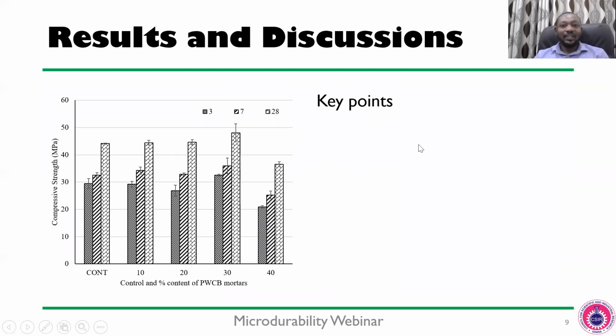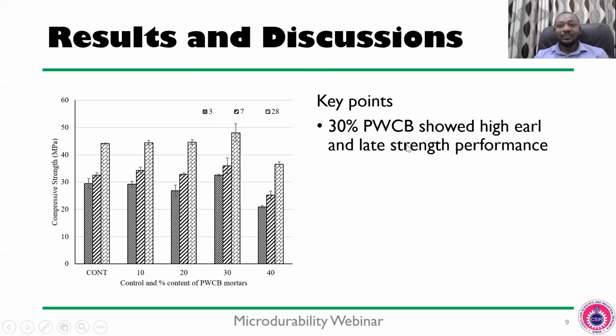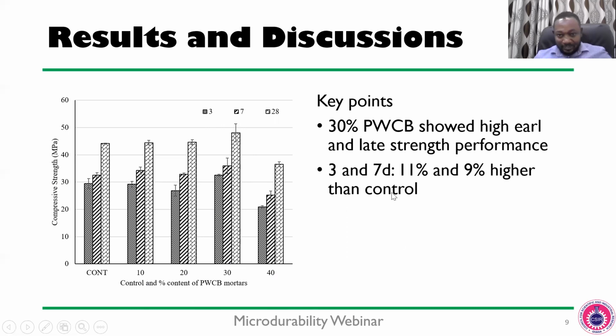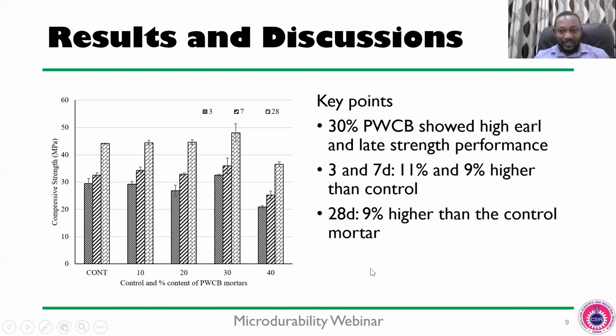So the results and discussion, these are the key points. Number one, we realized that 30% of the waste clay brick showed high early and late strength development. If we come to this graph, this is the control, and now at 3 and 7 days, 30% attains higher strength, which is the early strength, than the control. And then at 28 days, which is the late strength, it was also higher than the control. Comparing it to the other percentages, it was higher than 10, 20, and 40%. So at 3 and 7 days, it was 11% and 9% higher than the control, whereas at 28 days, the 30% waste replacement was 9% higher than the control mortar, which is this one.